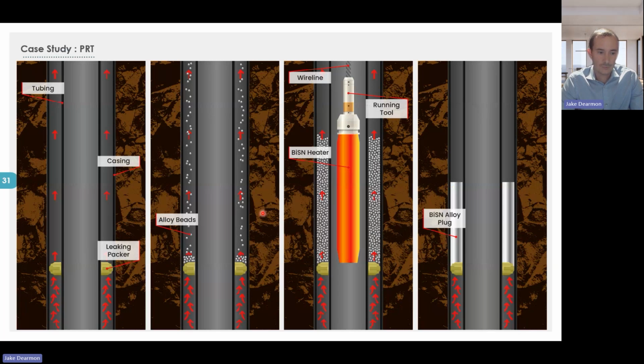Here's where we can kind of see the storyboard of this. So you have a leaking packer. You deploy the beads into the annulus. Those beads settle on top of that packer. We then run in with a thermite heater on the inside. We activate that heater, which warms up this entire area, allowing the alloy beads to melt without damaging the completion, because you are warming through that production casing or that tubing. And create a new packer in situ without having to pull the completion.